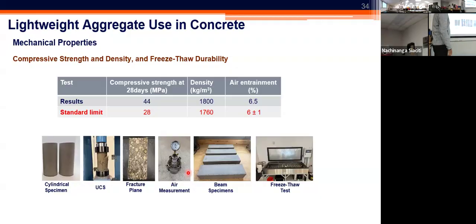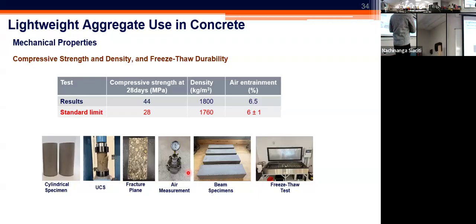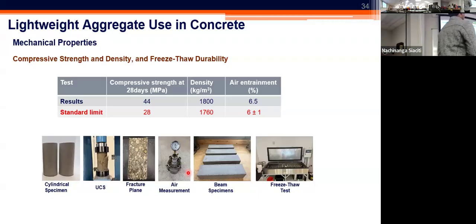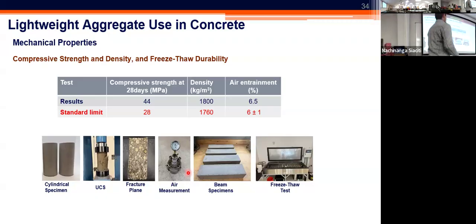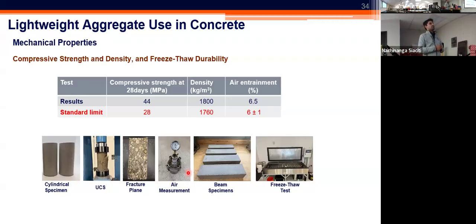So we were comfortable in the sense that the strength was achieved fairly easily, but we also were concerned about the potential freeze-thaw damage, especially if you imagine using this lightweight aggregate in Colorado, where it would be subjected to freeze-thaw cycles. So we wanted to see how the freeze-thaw may potentially affect the performance of these samples. So we made some beam samples, put them into a chamber, and then exposed them to freeze-thaw. This test involves applying 300 cycles of freezing and thawing. And by doing so, you can evaluate the degradation in the dynamic modulus of the material as a measure of the damage. And as long as your new dynamic modulus is at least 70% of the starting point, then the material can be considered as successfully passing this test.